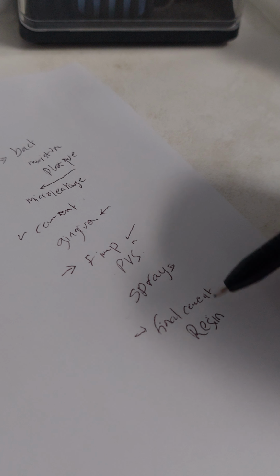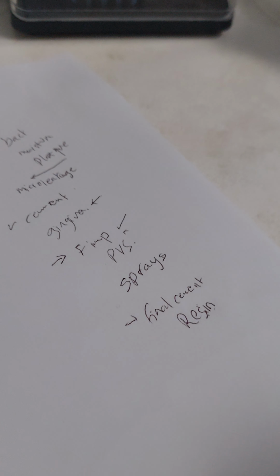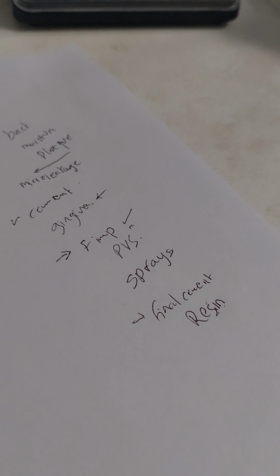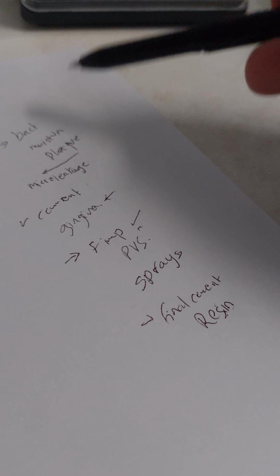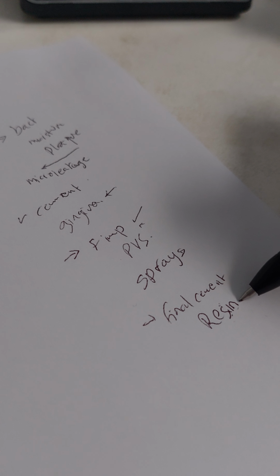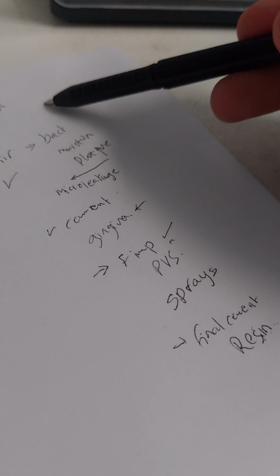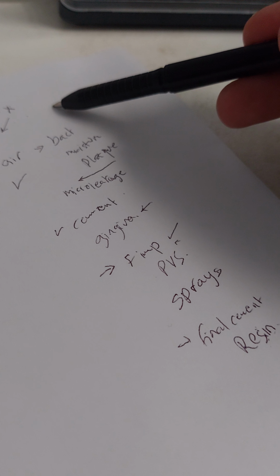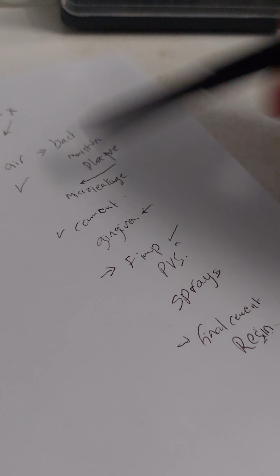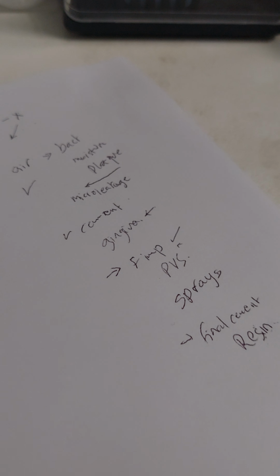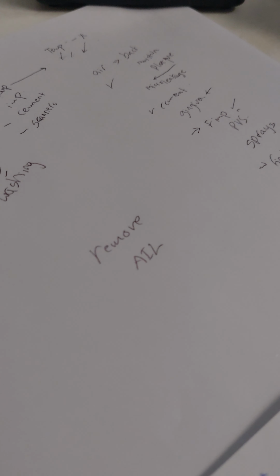So the final cementation of the resin will not adhere to the tooth surface and will cause microleakage, failure, and debonding afterwards. So debonding at the permanent cementation, debonding at the temporization stage, all happen because of the presence of this layer. To make a long story short, remove the air inhibited layer of composite in any procedure that you do. Thank you very much.